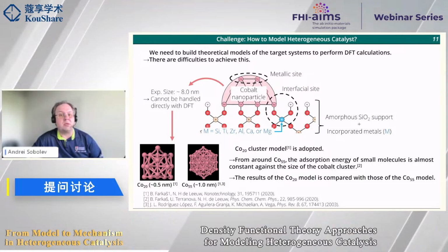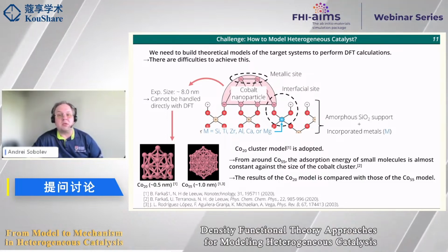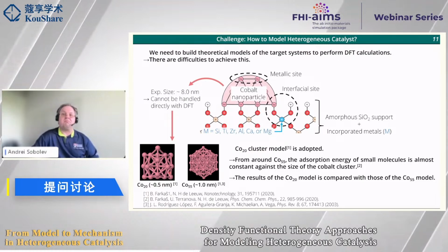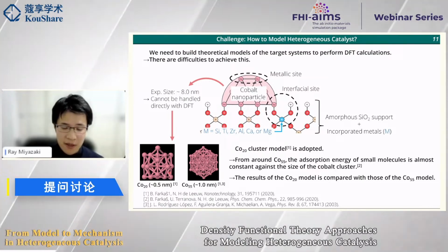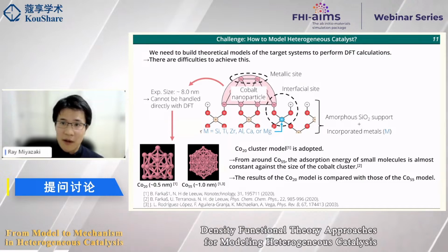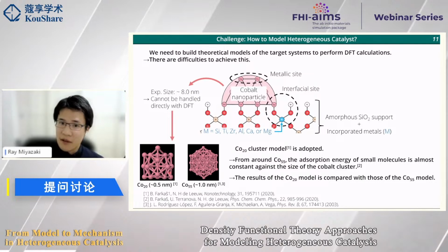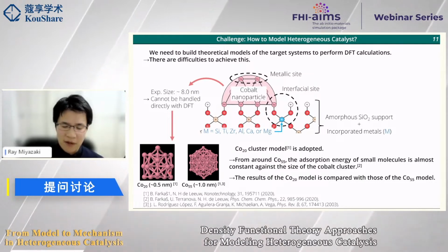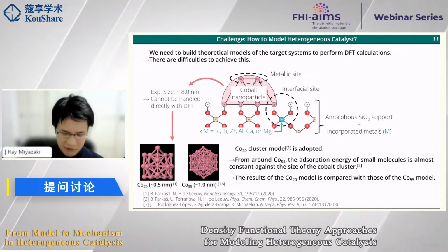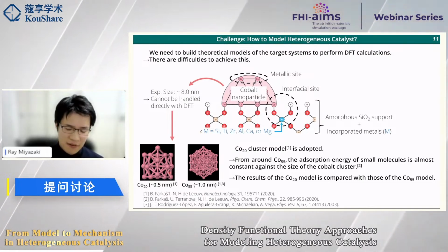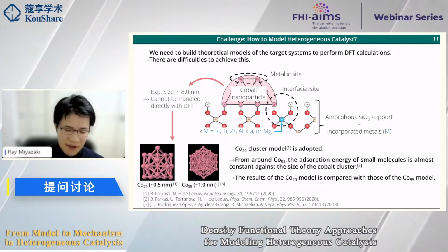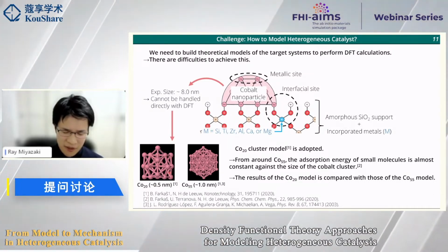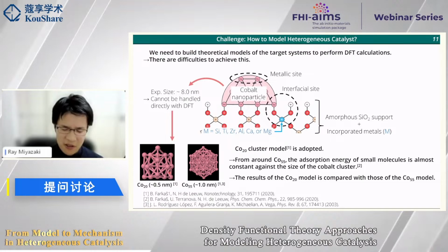For molecules, especially in systems where intermolecular interactions are important, it's essential to include van der Waals corrections for accurate results. Yeah, right. Before performing this calculation, I checked the accuracy of RPBE and RPBE with van der Waals correction. For this, I adopted the Tkatchenko-Scheffler type van der Waals correction. I investigated the CO adsorption energy of carbon monoxide on the cobalt surface, because there are experimental reports for the adsorption energy and the vibrational frequency of CO on the surface.